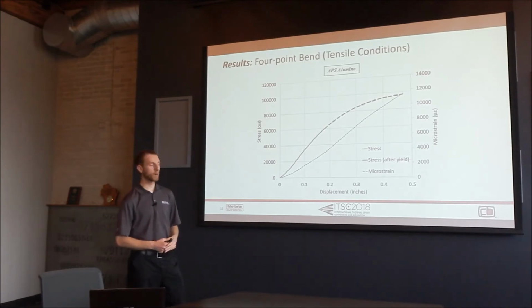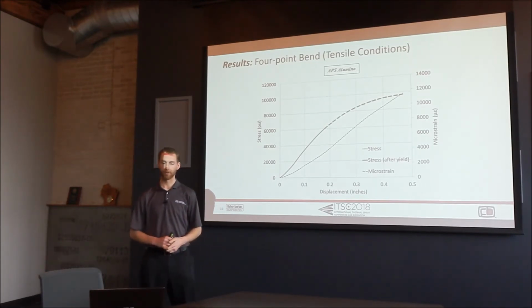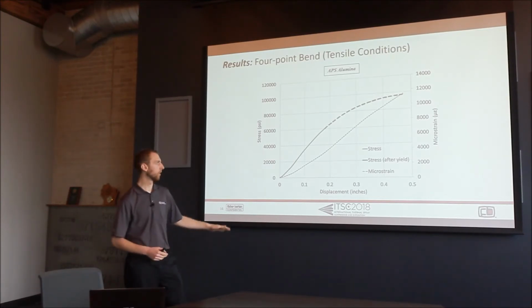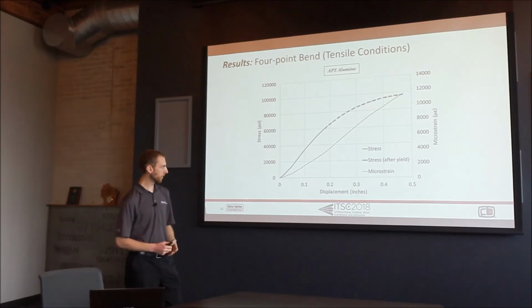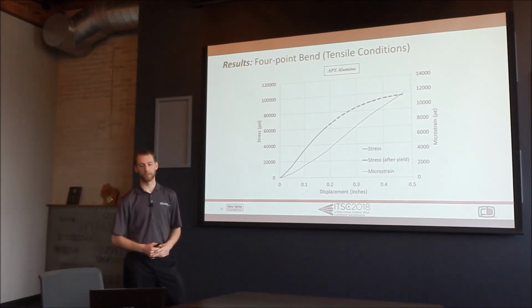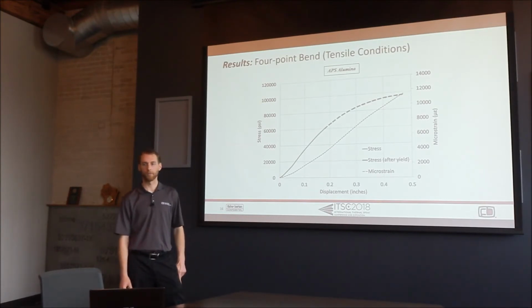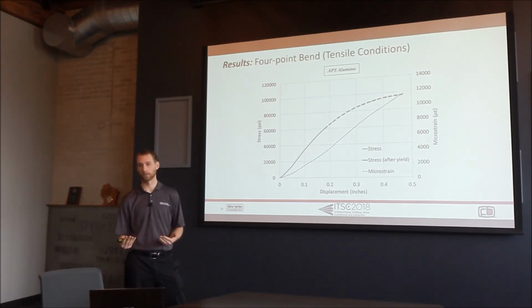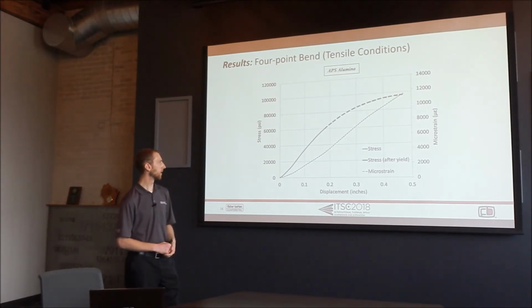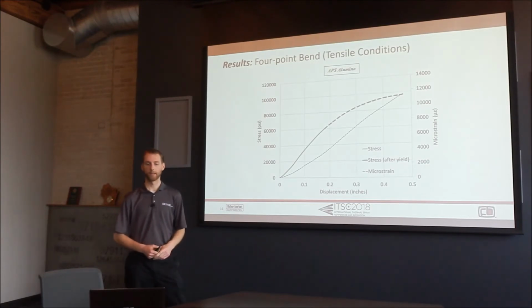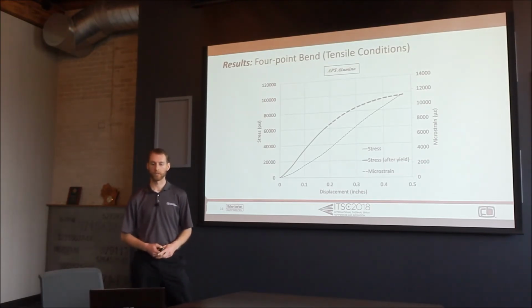With the atmospheric plasma sprayed alumina, we have a similar type of curve, but there is a little bit different behavior when it comes to the strain on the lower line. It's not quite as linear as the last set of data. Although we haven't studied it, we think there's some other behavior going on with the coating, where you have some splat boundary sliding that results in non-perfectly linear strain as the displacement progresses. But still, the substrate yielded at about 60,000 psi. We do have coating adhesion still well beyond that yield strength, and again, well beyond what C633 might tell you.